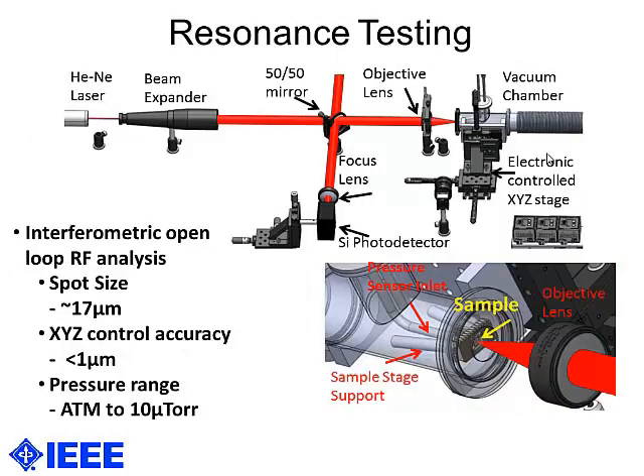Our resonant test setup consists of a helium neon laser with a beam expander, the standard interferometry setup with a 50-50 mirror, an objective lens, and our vacuum chamber where the sample is held. We have an electronically controlled XYZ stage with sub-micron accuracy and an amplified silicon photodetector. Down here is a zoom in of our sample stage.